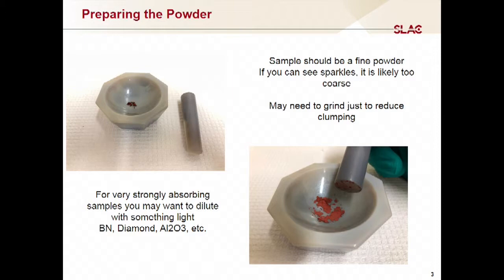Something that looks like powdered sugar is preferred. So it should actually be a pretty fine powder. And a general thing that you can do is if you can see sparkle, you should keep grinding it. There are other ways that you can do this as well. You can get a very fine set of sieves, and anything that passes through the finest sieve, which is going to be somewhere in the order of maybe 30 to 100 microns, if you have a very fine sieve, will go through, and that's usually a pretty good size. It might be a little bit on the big side, but it would be all right. And so you want to continue grinding.